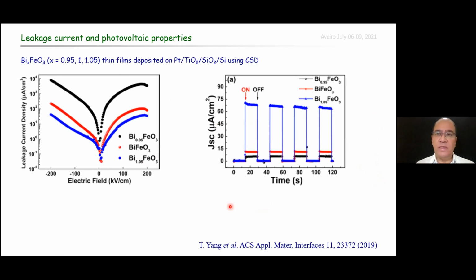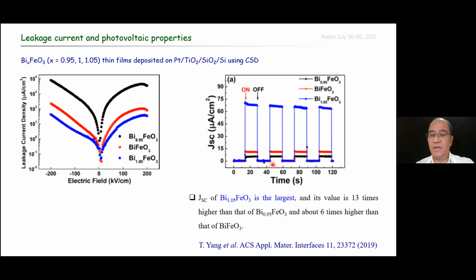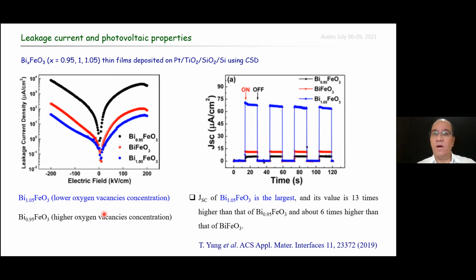Finally, they concluded that the photovoltaic response in their BFO films was intrinsically related to the oxygen vacancy concentration. In other words, lower oxygen vacancy concentrations lead to the blue curve in this leakage current and to a high photovoltaic response, as observed in this figure, while a low photoconductivity response was observed in BFO film with high oxygen vacancy concentrations.